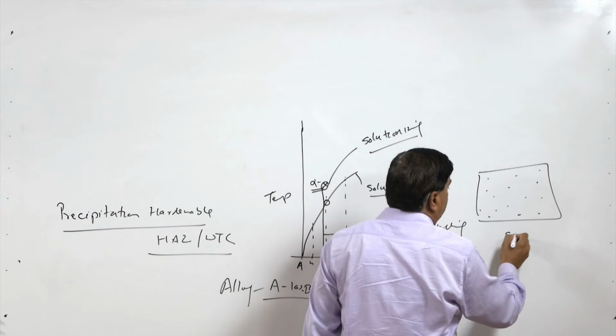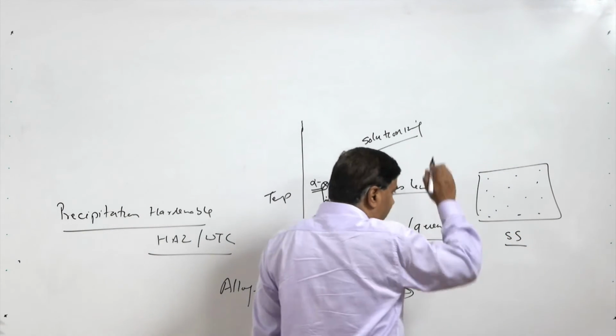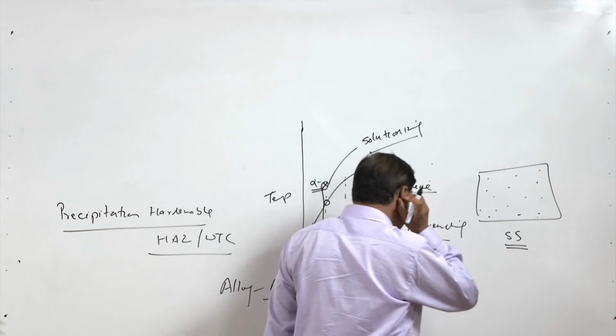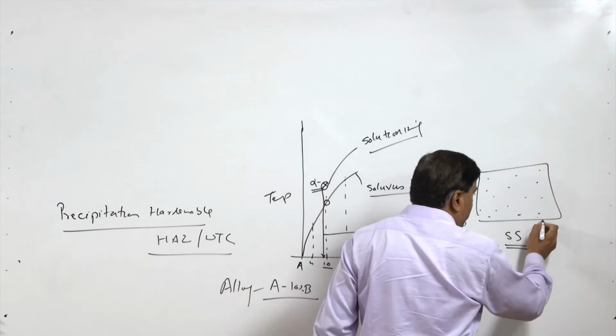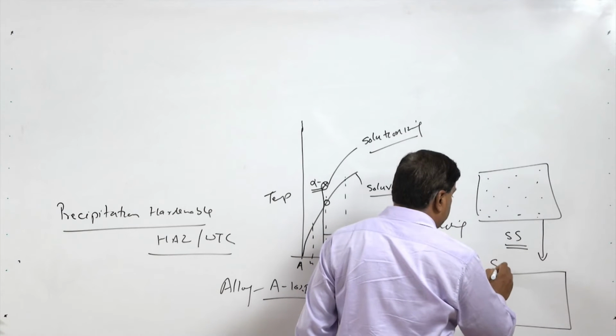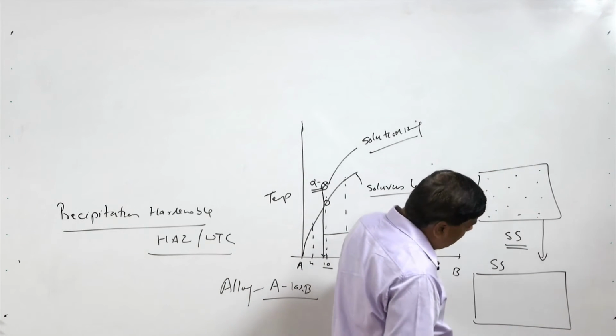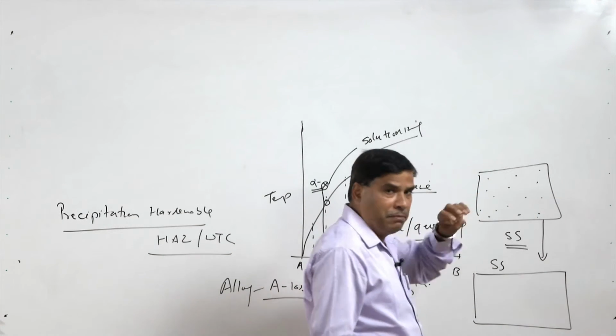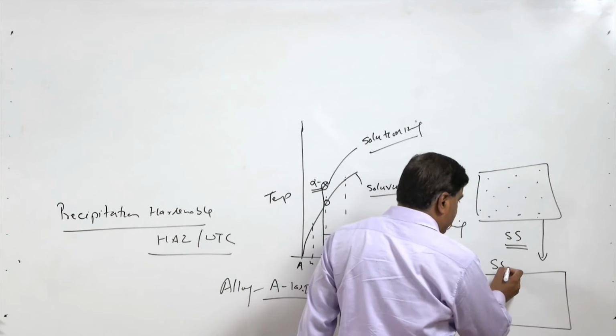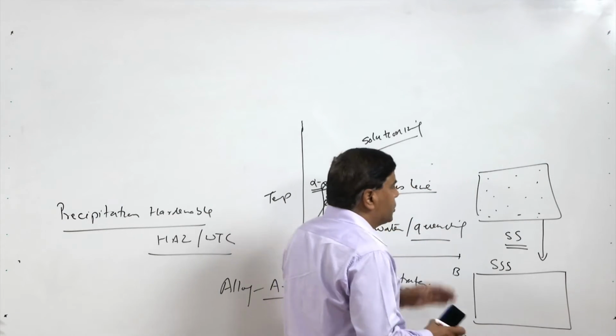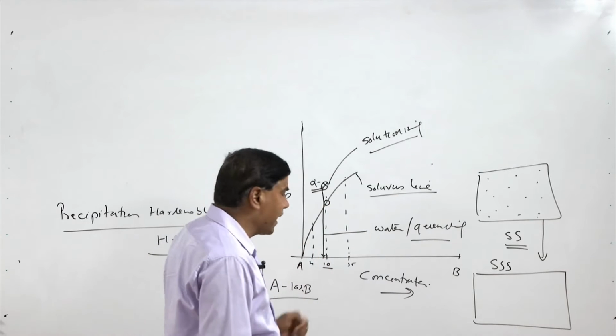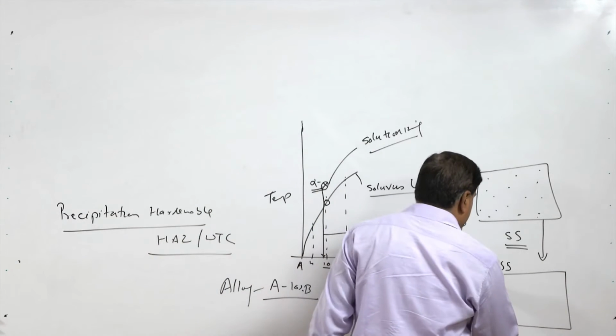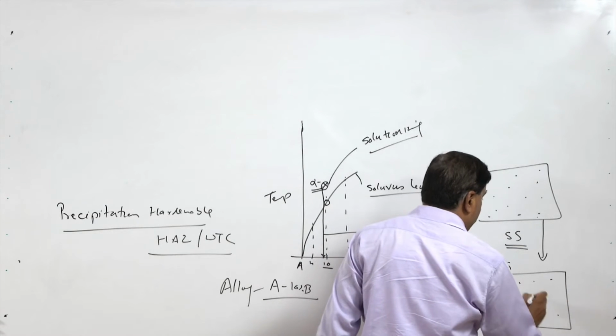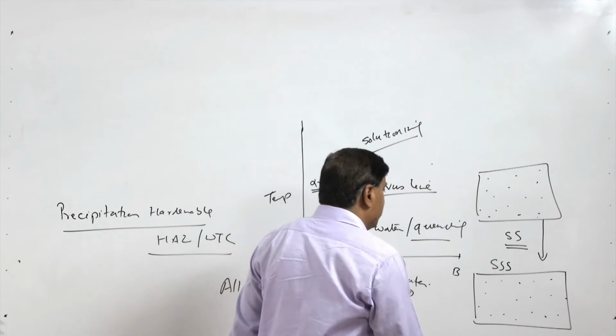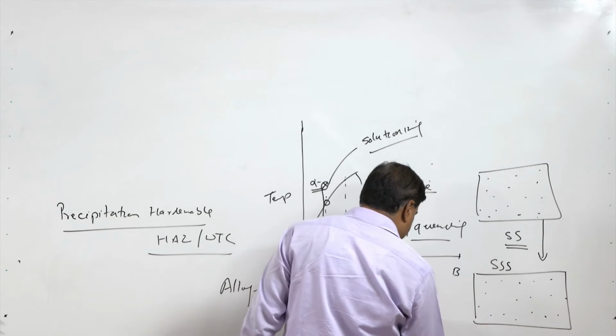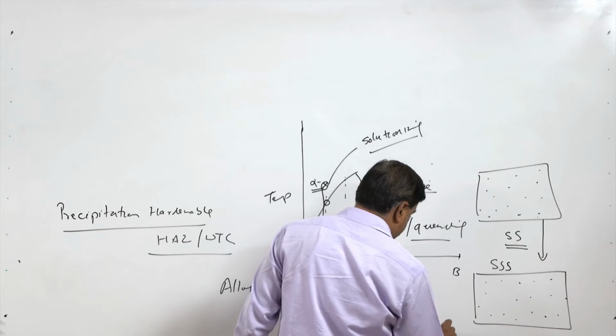So, since during the solutionizing we have got uniform presence of the alloying element in the matrix in the form of a solid solution, which may be interstitial or substitutional, rapid quenching of this solid solution forms the supersaturated solid solution, because it does not allow any diffusion to take place, and the solutes will be retained wherever they are present. So, this in turn results in the supersaturated solid solution, wherein the solute will be present in the matrix much more than its capacity to accommodate, meaning above the solubility limit. So, the alloying elements are present at room temperature above their solubility limit, and that is why it is called supersaturated solid solution.